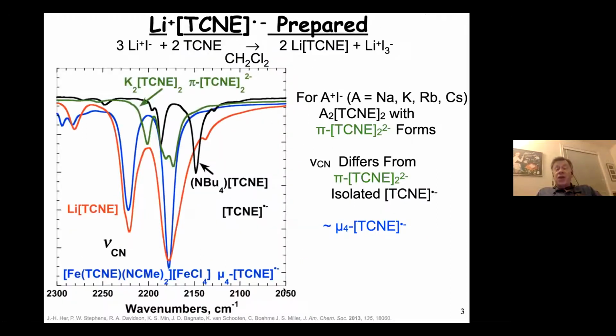However, when you react it with lithium, you end up with a completely different compound, with 1 lithium per TCNE instead of 2 lithiums for 2 TCNEs. Again, you form lithium triiodide. The infrared spectrum is shown in red, and it's completely different from the green spectrum for the 2- dianion, and completely different from the black for the isolated radical anion. But it is similar to what we see for the mu4 TCNE radical anion illustrated in blue. So this material has a different infrared spectrum, suggestive of forming a TCNE radical anion that's bridged to 4 different cations.